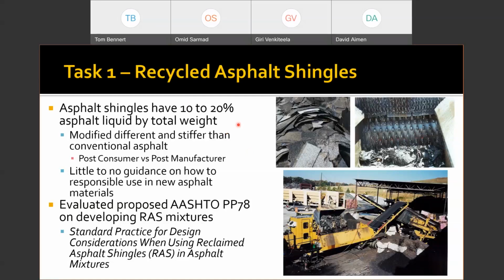So there's a possibility of including these in an asphalt mix because of the compatibility, or somewhat of a compatibility, between the binders. There are some significant differences, though, when we talk about the asphalt, because the asphalt in these shingles is much stiffer, and it's modified in a way so that obviously when it's very hot out, that asphalt doesn't drip down the side of your house. So the stiffness of these materials is much different than what we would conventionally use. And at the time, there was a little bit of pressure on the New Jersey Materials Bureau to take a look at this again. It was in the specifications, but people hadn't used it in quite a while.